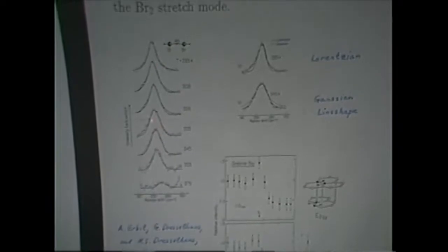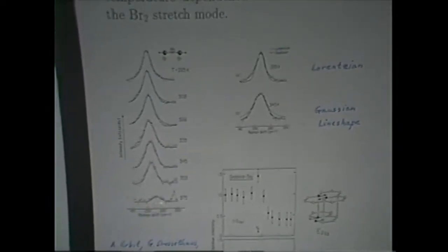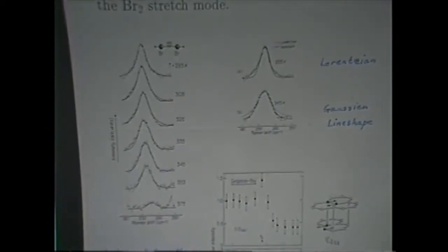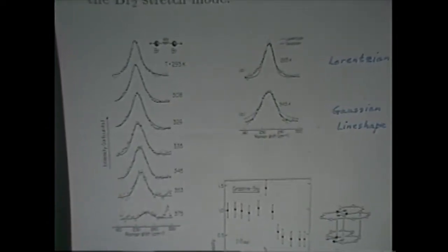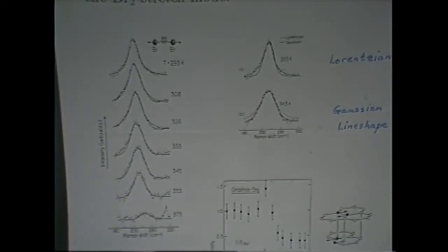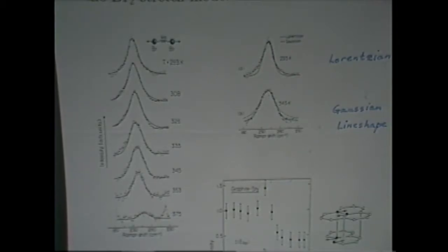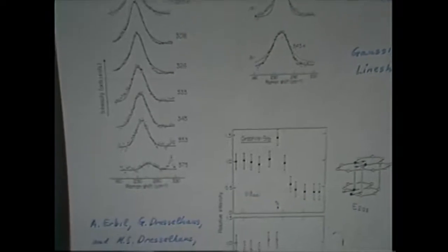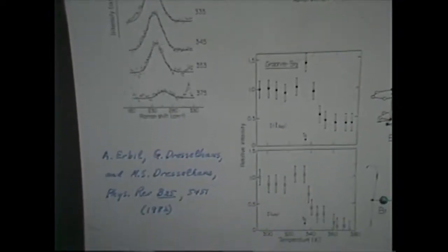So here's a Raman spectrum of the bromine stretch mode in bromine intercalation compound. And it's a nice Lorentzian line for a while, and then the line shape seems to change, and all of a sudden it disappears. And the disappearance of the line corresponds to a melting transition. But before it melted, we had a line change. Why should there be a change in line shape? At room temperature, the line shape is Lorentzian, which indicates that you have a homogeneously broadened line. But then when the temperature went up just by a few degrees, 345 degrees, for example, no more Lorentzian line shape, but Gaussian line shape, which indicates inhomogeneous broadening.